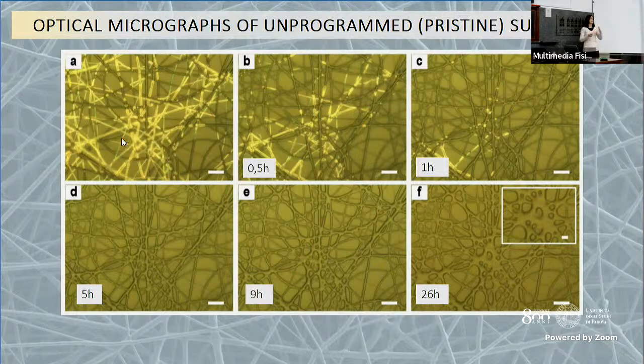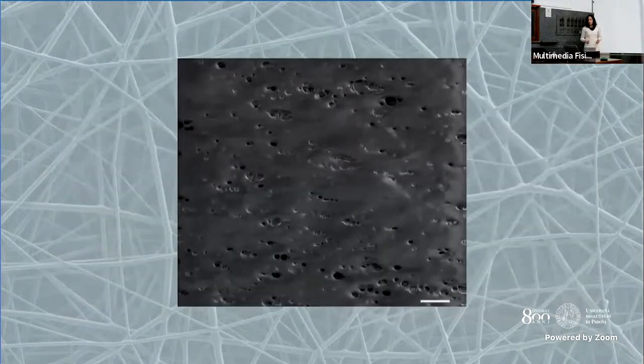But if you keep the sample in the ambient environment for, say, half an hour, 1 hour, or 9 hours, or 26 hours, you see that slowly you lose the shape. So they start something like melting, because as I mentioned before, without UV light they are not stable. So finally, without UV light, instead of fibers, you get something like this, a porous film.